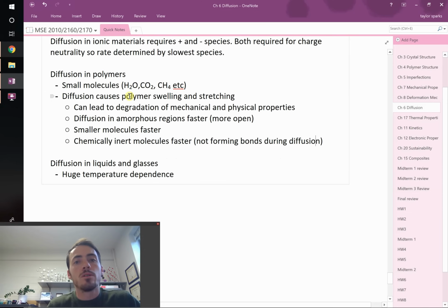They're also susceptible to swelling and stretching, which can cause degradation of properties. In fact, if you do swell a polymer and then you measure its diffusion, it's going to be much higher in a swollen one. So when they make polymer electrolyte membrane fuel cells, which they're using for some vehicles, right, PEMFCs, polymer fuel cells, they intentionally soak the material that's going to diffuse hydrogen through it so that the hydrogen can travel faster in this swollen state, because it spreads those atoms out a little bit.